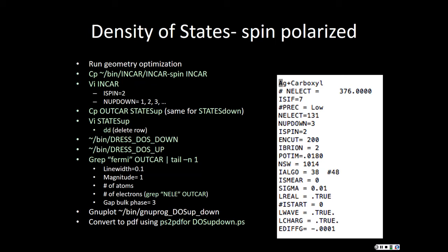Well, so just one comment. When you were talking about that line that says the gap bulk phase, that's not always 3. The way I understand it is, depending on what material you're looking at, you put what the bulk band gap energy would be in that line. Oh, okay. I'm going to write that down. That's good to know. Unless Dr. Killen has a different answer, but that's the way I remember it. Yep, that's correct.